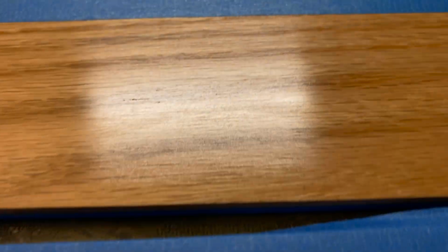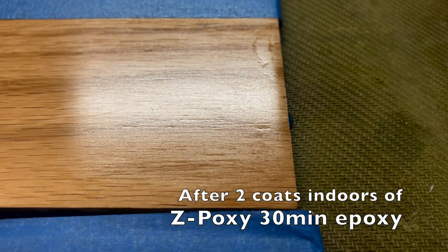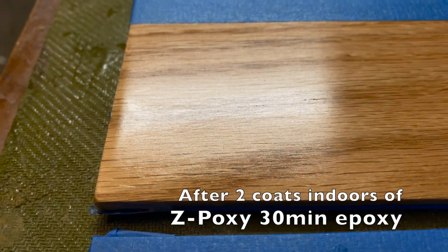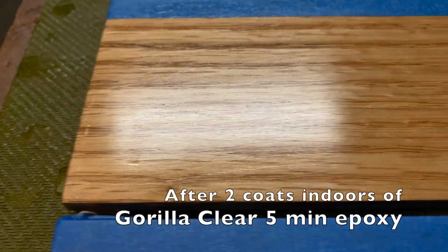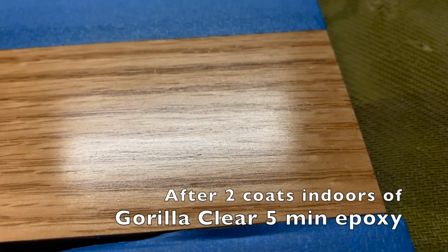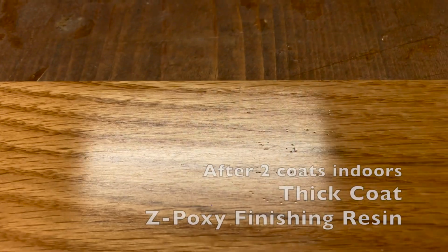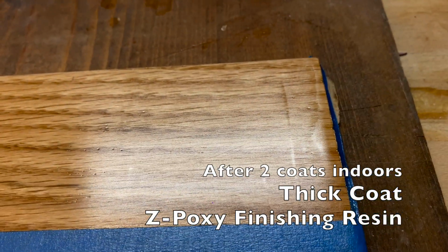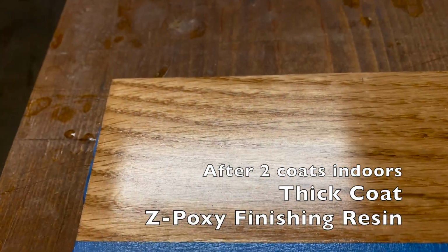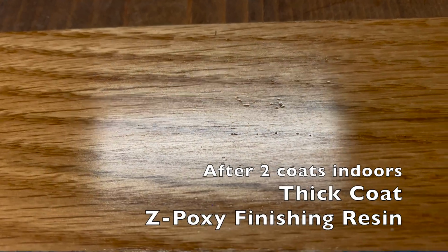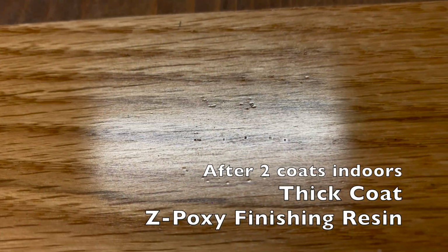The Z-poxy 30-minute epoxy seemed to fill the grain, as did the Gorilla Clear 5-minute epoxy, which makes sense because they are both inherently thicker formulas than the finishing resins. And the thick application of the Z-poxy finishing resin was also a success after 2 coats. Although it's interesting that I can barely see some air bubbles left behind here on the thickly coated board.